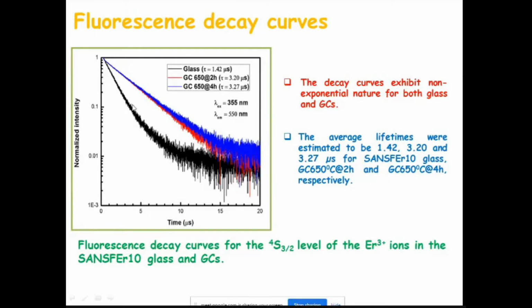For example, you can see the black line is a glass, and the blue and red is a glass ceramic. This decay time is very, very short, whereas this decay time is very, very long. So in the glass ceramic, I am able to see the lifetime is longer, whereas in the glass the lifetime is shorter. So a glass becomes a glass ceramic, and I have the advantage of lengthening its lifetime. This is the way optical properties, particularly luminescence properties, can be enhanced from glass to nano glass. This is what we are doing.